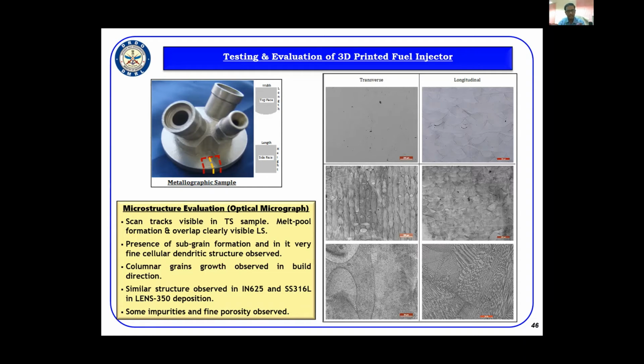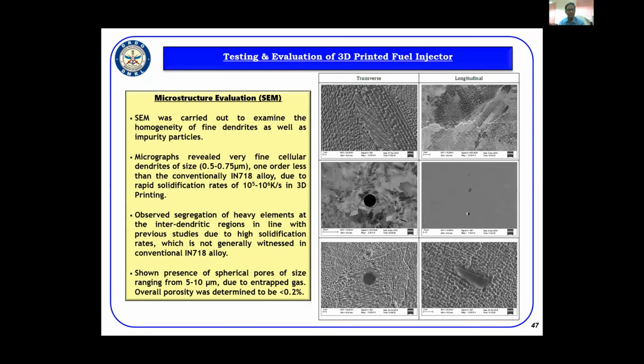But we have seen certain amounts of porosity, very fine impurities, and very fine porosity in the microstructure evaluation, which we have taken up for further analysis. So we went ahead with the scanning electron microscope to understand the homogeneity of fine dendrites as well as the impurity particles. The microstructure revealed very fine cellular dendrites, one order finer than 718, due to the very high solidification rates of 10 to the 5 to 10 to the 6 in this process of 3D printing. We have also seen heavy elements segregated in the interdendritic region, due to high solidification rates, which is not generally seen in the conventional material. This type of segregation was not visible there, but we have seen it here.